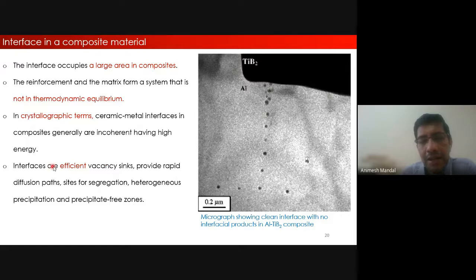And these interfaces are efficient sinks, or vacancy sinks, which can provide a rapid diffusion path. So the more the volume fraction of interface in your material, the more you are changing the diffusion speed, or the rate at which your solute elements can diffuse from one end to the other. These interfaces can also act as sites for segregation of different solutes.